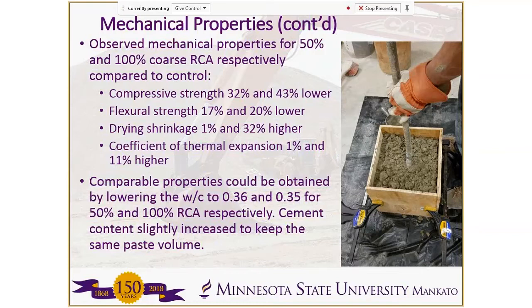We also did some other experiments to see if we can adjust the mix design such that the mechanical properties are somewhat similar. So we found some comparable properties if we lowered the water cement ratio to 0.36 for 50% RCA, and if we lower it to 0.35 for 100% RCA. We had to increase the cement content slightly so as to keep the paste volume the same.